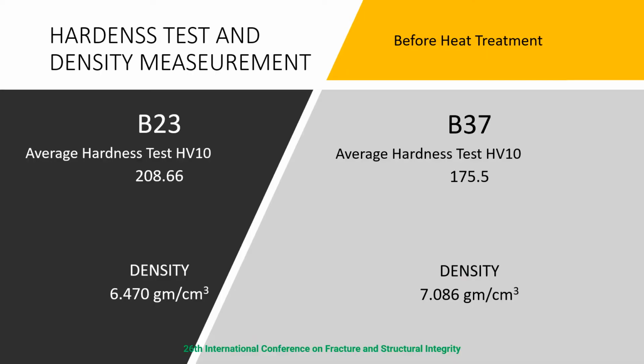A hardness test and density measurement were carried out on both the alloys before the process of heat treatment. For this, a Vickers hardness test was done. As you can see, the average hardness for B23 is 208.6 and the average hardness for B37 is 175.5. Later, a density measurement was carried out, where the density of B23 was 6.47 grams per cubic centimeter and the density of B37 was 7.08 grams per cubic centimeter.